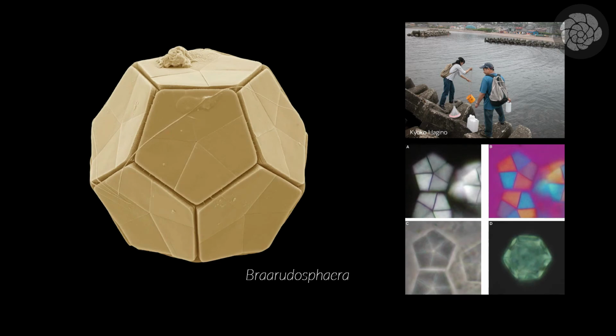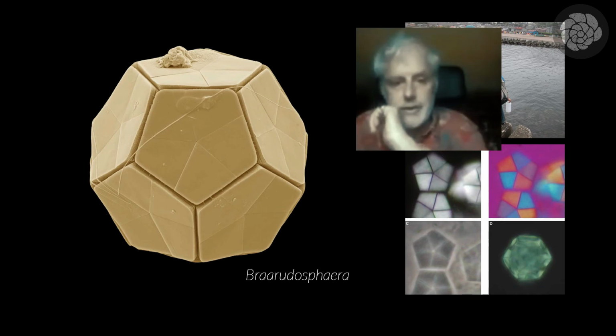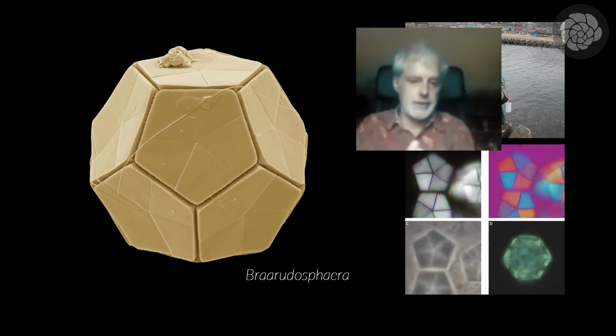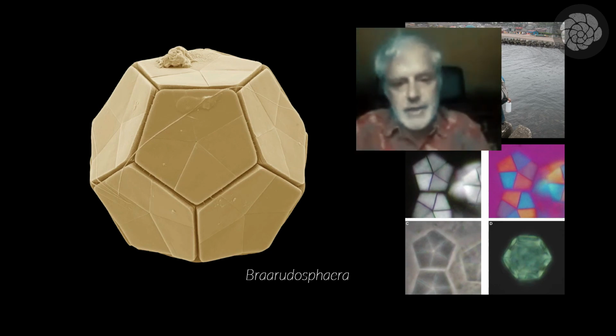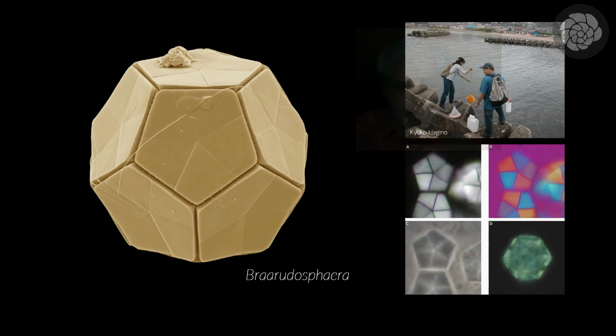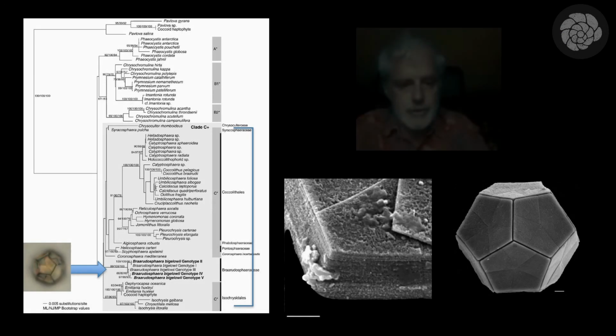nanoliths, which then form a nice dodecahedral sphere. And we know from beautiful work, particularly by Kyoko Hagino, that they're definitely not heterococcoliths. The alternate life cycle phase in this case is a haptophyte which non-calcifies. The calcification occurs around the outside of the cell, they aren't formed inside the cell and exocytosed. In terms of the biomineralization, they're very different. They've got tangential calcite C-axes rather than radial, and these 5 units each behave as a single crystal unit with a tangential C-axis.